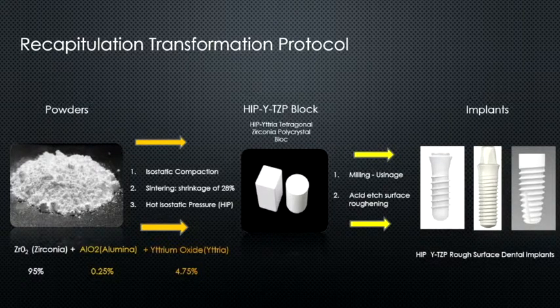They get all mixed together, compacted, sintered, and in the hot isostatic press, you get these blocks, similar to your CEREC blocks that you have in the office. Similar, not exactly identical. And then those blocks get milled into different types of implants, different brands of implants, and in some cases they get resintered after the milling. Some get sintered before and then milled. It depends on the company. Every company has a protocol.